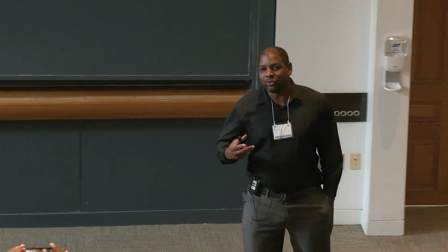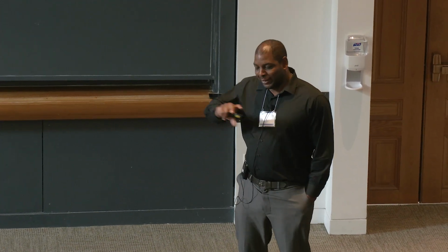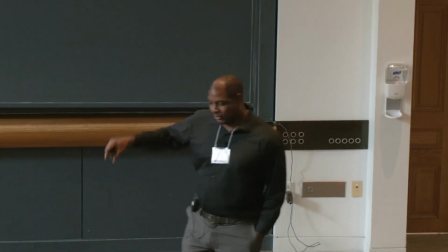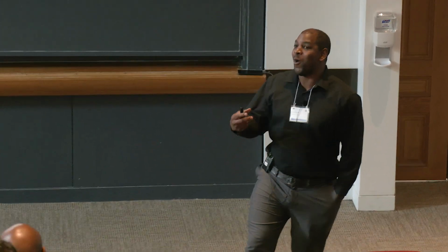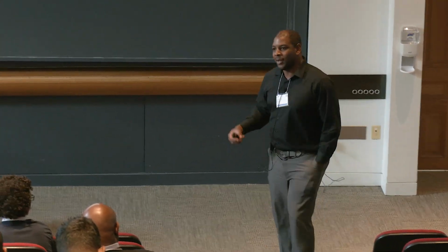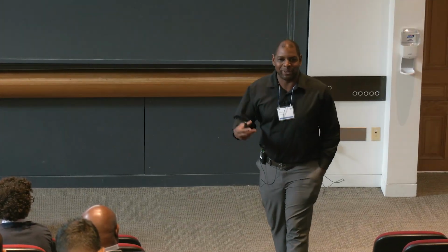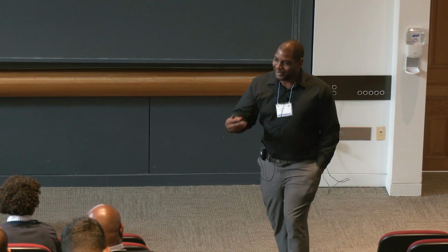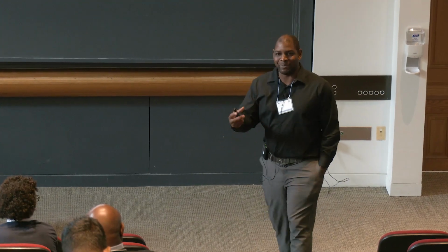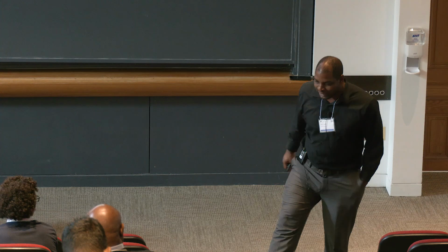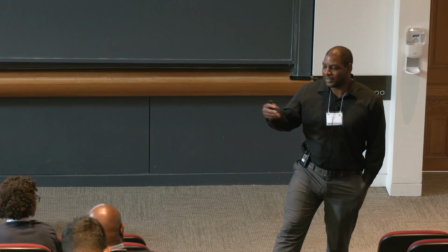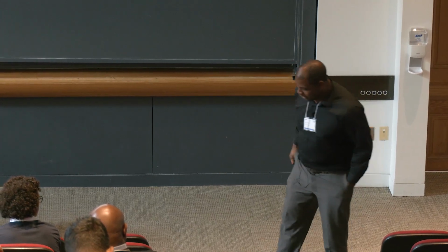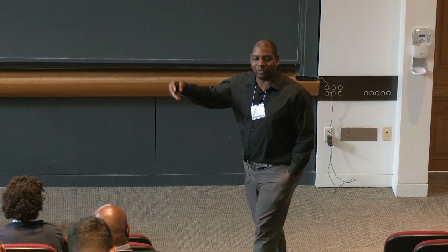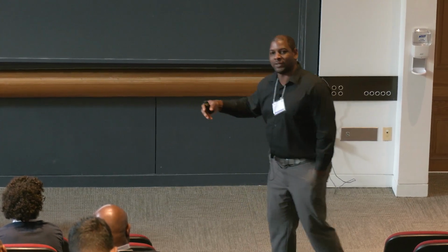One part that is, I think, very interesting is that there's a common theme that goes throughout most of the materials talks, and this is the idea of disorder or defects that we've been talking about, and that we actually want these things to happen in materials, right? Which is kind of strange because they're called defects. You would think you don't want them. So we saw this in the nitrogen vacancy centers that turned the diamonds pink. For Serena's talk, we saw this actually helps stabilize these vortices, and now in Divine's talk, he broke this crystal symmetry order by making these interfaces.